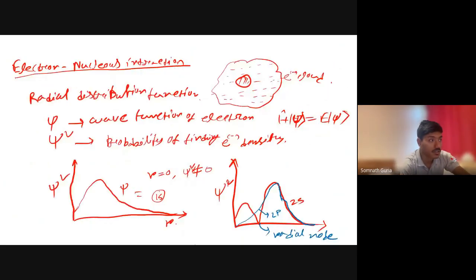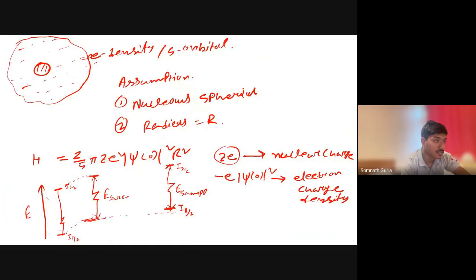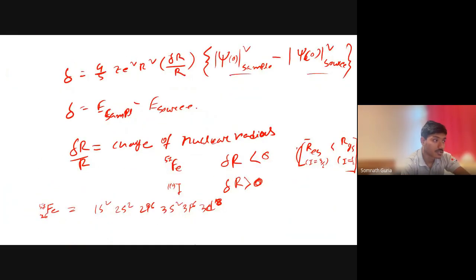We will get that curve, and it depends on how much energy we are providing. That energy is required by the electron distribution of my iron center. Further, only the s orbital of iron, or the s orbital of any nucleus, is responsible for some electron density at the nucleus, which comes from the radial distribution function of the s orbital. Then we found an energy term, that is the delta. This delta is 4/5 Z squared R squared times delta R by R, times the sample's psi squared, the probability of electron density, minus the source's. Depending on that, we can calculate how much energy we are required to move by the source.